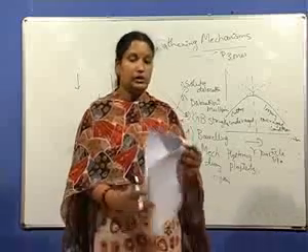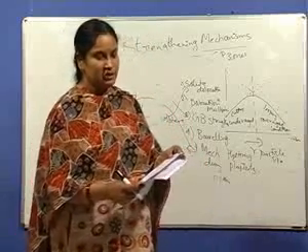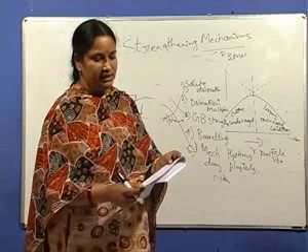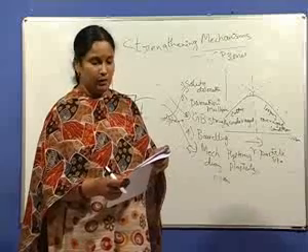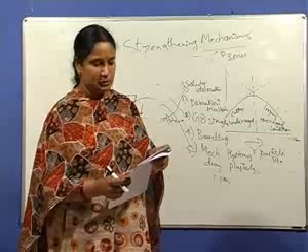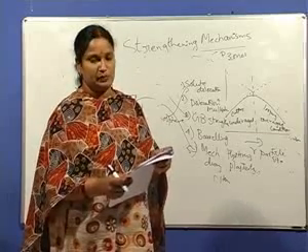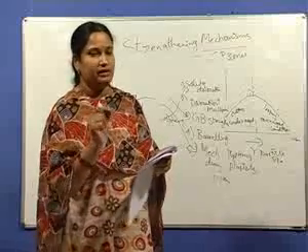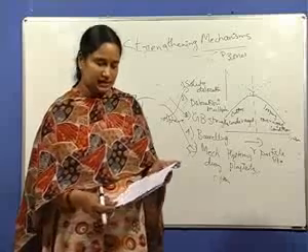Question number 42. In today's class, I have explained about precipitation hardenable alloys. During low temperature plastic deformation of an under-aged precipitation hardened alloy, dislocations: climb to completely avoid the precipitate, loop around the precipitate, cross slip to completely avoid the precipitate, or cut through the precipitate. When the precipitates are very fine, the dislocation cutting mechanism operates. So the option is D.